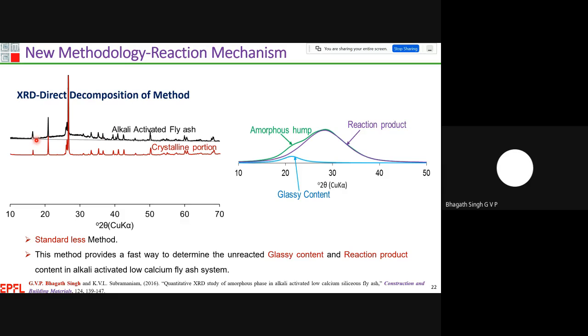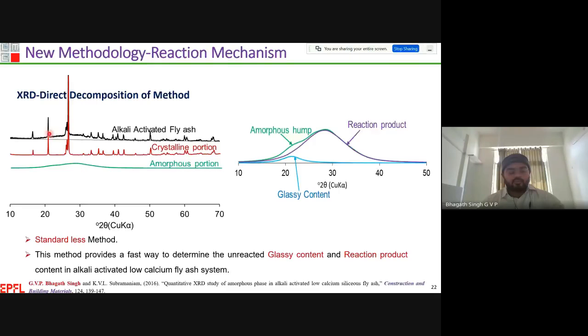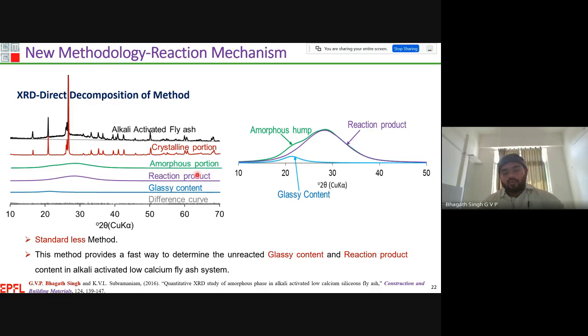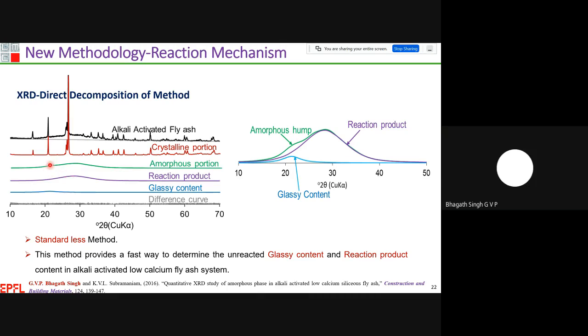Then by using Pawley refinement, I have separated the total crystalline portion as well as the total amorphous portion. And as I have explained earlier, the total amorphous portion is considered to shift from a lower 2 theta angle to a higher 2 theta angle after the activation process. Then by using a nonlinear fit algorithm, I have focused on this region, especially from 15 to 42 degrees 2 theta angle. And this is the amorphous hump.